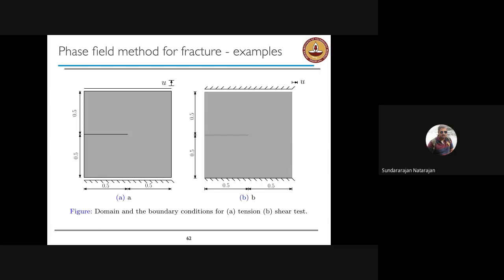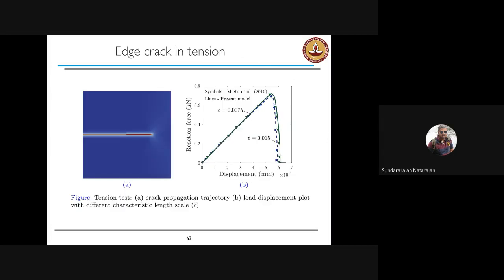So in the first case, you will expect that the crack grows straight until it reaches the external boundary. In the shear case, because of the boundary conditions and the load applied, you will see that the crack deviates, takes an angle, and goes to one of the fixed boundaries. So this is a plot coming from solving the phase field equation. What you see here is the crack trajectory.